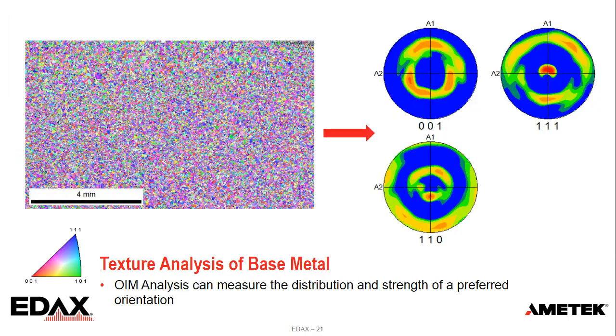Once we have that, we can do what we call texture analysis. Texture analysis is just looking at the orientation distribution of the measured orientations. So it fits a function that describes the distribution. From that, we can get an idea of the strength of a preferred orientation. I'm sorry, as I look at this, I realize I didn't put the color scale, but essentially these colors on the pole figures, these images on the right, show the spatial projection of the orientations onto the sample reference frame.